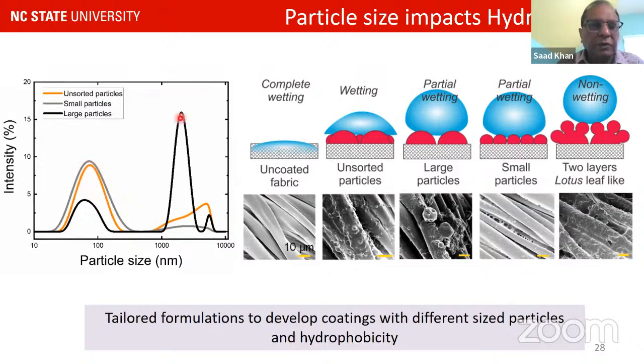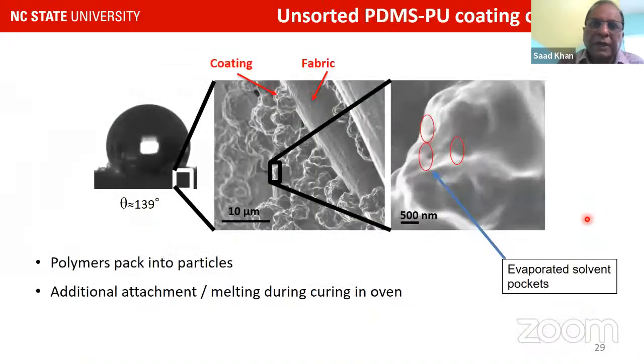You have some smaller, some larger, and depending on how you coat them, you can get partial wetting to very little wetting. These are some of the pictures shown here, where we have gone from pure cotton to applying 2 layers of these coatings using either one type of size or both sizes. So let me probe this a little bit more. This is the fabric, and these are the coatings. The coatings are pretty well absorbed onto the fabric. The contact angle, as I said, is around 130, 140.